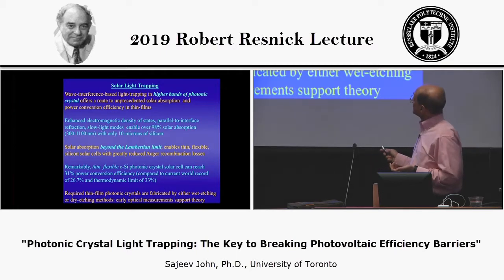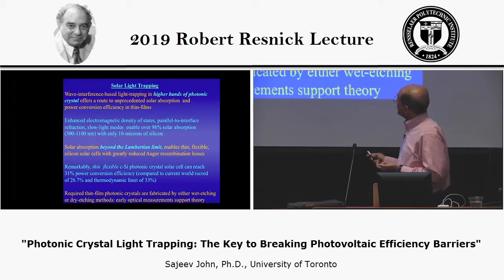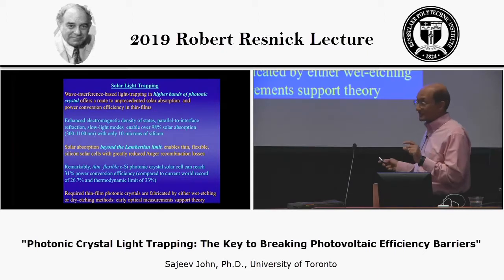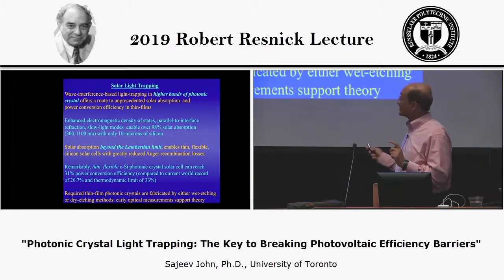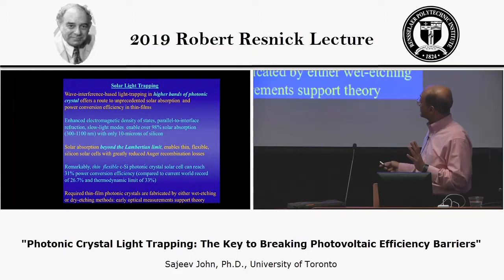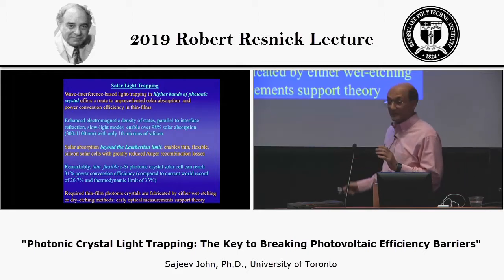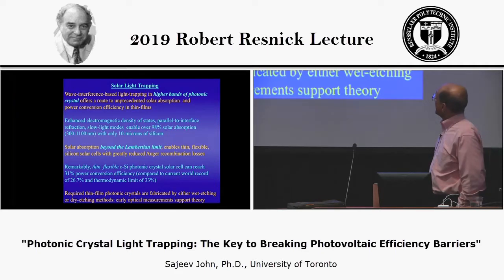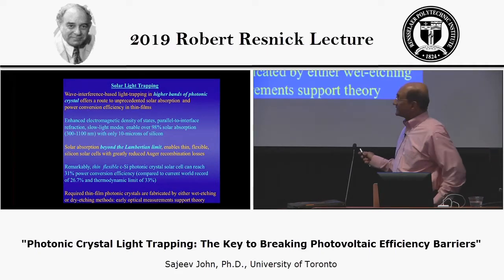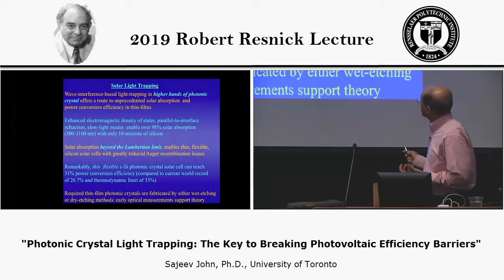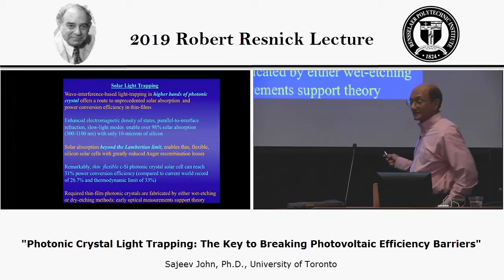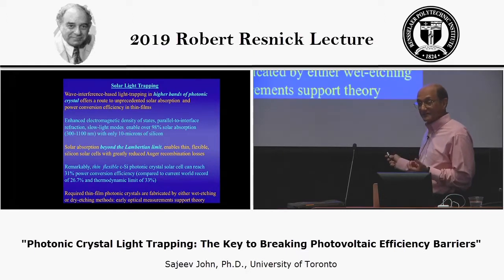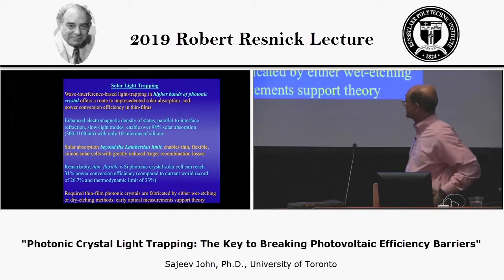And in fact, what we've shown is that in a film of silicon, considered a thin film of only 10 microns of thickness, it's actually possible to absorb 98% of the sunlight over this broad spectrum between 300 and 1100 nanometers. And this solar absorption beyond the Lambertian limit allows us to make silicon structures much, much thinner than would traditionally be possible. And those are thin as well as flexible, and it greatly reduces one of the major recombination loss mechanisms in silicon. That's what allows the efficiency to go up.